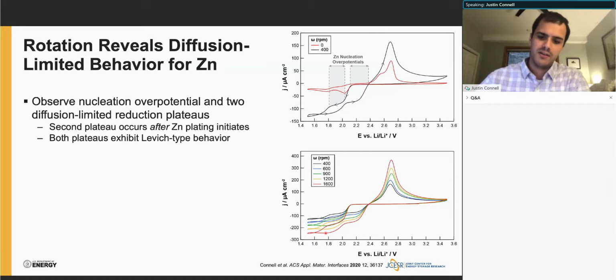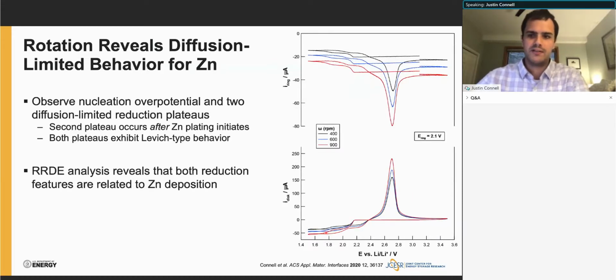But to confirm that they are indeed related to zinc deposition, this is where the ring disc technique comes in very handy. We drive constant zinc deposition on the ring electrode by holding the potential at 2.1 volts, corresponding to this first reduction plateau where we know zinc metal deposition is taking place. As we go to more and more negative potentials at the disc, we see a decrease in the ring current corresponding to consumption of zinc by the disc electrode. We see two distinct decreases in that current density, indicating that both of these reduction events are related to the consumption of zinc at the disc electrode.